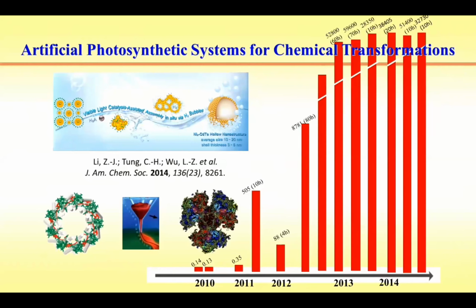In comparison to well-developed traditional approaches, the hollow structures are formed in situ by the photo-generated hydrogen bubbles at room temperature. The average diameter and shell thickness of the nanospheres ranged from 10 to 20 nanometers and from 3 to 6 nanometers, which are rarely reported in the literature. And the most important thing is the hollow structure shows excellent photocatalytic activities and stabilities for the generation of hydrogen. Compared with the biological systems and the biomimetic systems for hydrogen evolution from water, the discovery of the artificial photocatalyst established a new paradigm for creating photocatalysts that are highly active, robust, and cost-effective in aqueous media.